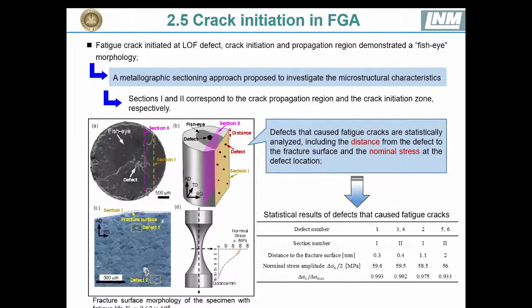And in addition, the internal crack induced crack is also observed in this analysis, as shown by SEM, and also here at a different section. We found some different cracks, secondary cracks, and also statistical analysis, and they are listed in table 1. Later on we will do some analysis on table 1.